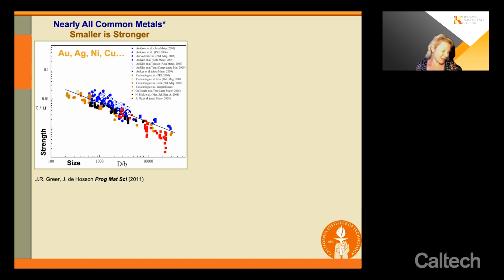Now, there's a reason why we decided to work with the nanoscale. If you look at some common metals like gold, silver, copper in their single crystalline form, and then you plot their strength as a function of their size, what emerges is the so-called size effect, where smaller is stronger. What I mean by that is that this is a log space, and this linear slope actually represents a power law. And that is, if you take your earring, which is very malleable, and reduce its dimensions to about 200 nanometers, it becomes as strong as steel.